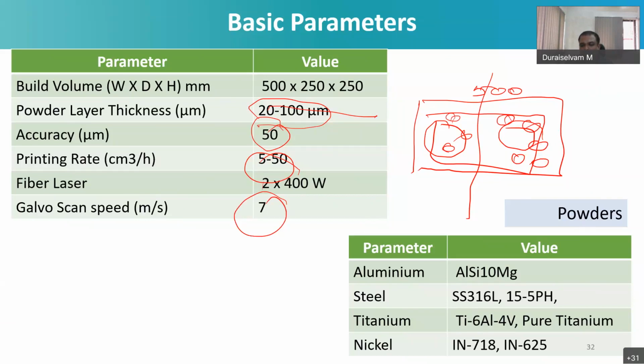And multiple materials are possible with our printer. In aluminum alloy, we have aluminum silicon 10 magnesium. In steel, we have 316L and 15-5 PH. Titanium grade 5, which is medical grade, titanium 6 aluminum 4 vanadium, and we have pure titanium also. And under the Inconel alloys, we have Inconel 718 and Inconel 625. And this multi-material capability is possible right now.